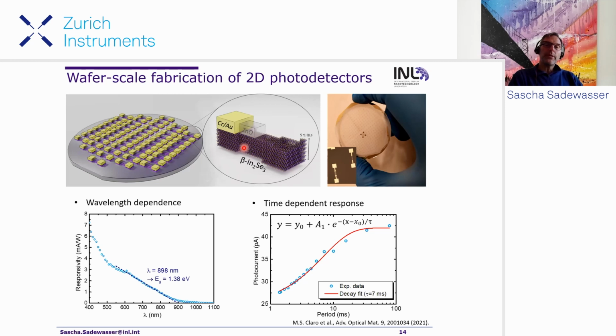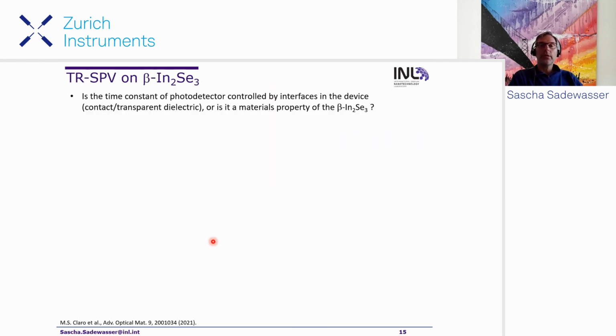And even on the edges when you do the etching. So these trapped charges can generate additional electrostatic fields that then lead to different time responses of your device. Therefore our question was, is this time constant that we measured there related to the interfaces of the device, let's say at the contacts or the transparent dielectric that we use, or is it an inherent material property of the beta indium 2 selenium 3?